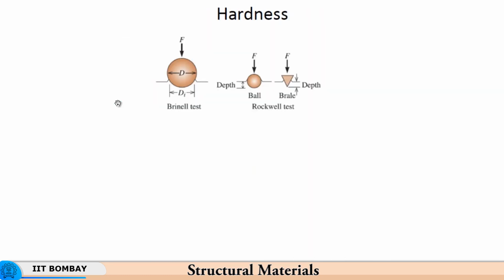Another property of the material is hardness, that is resistance to plastic deformation, and it is related with the permanent deformation. Now, you deform the surface with a Brinell test. You press the ball into the surface as in the Brinell test, and then examine the size of the impression. So, load divided by the area will give you the value of stress, under a certain amount of force. So, force is fixed here and the area of indentation is measured. So, smaller is the area of indentation, harder is the material, that is what it means.